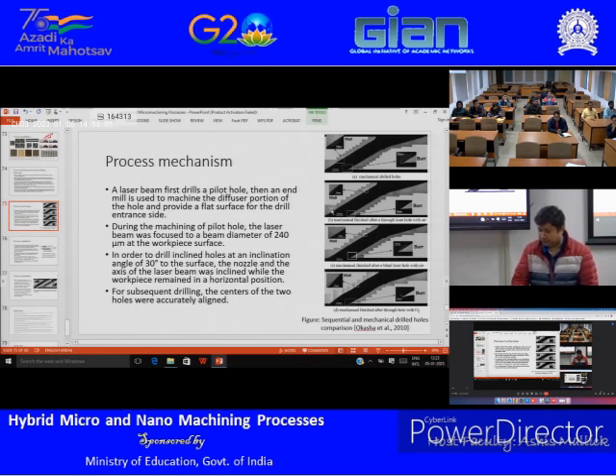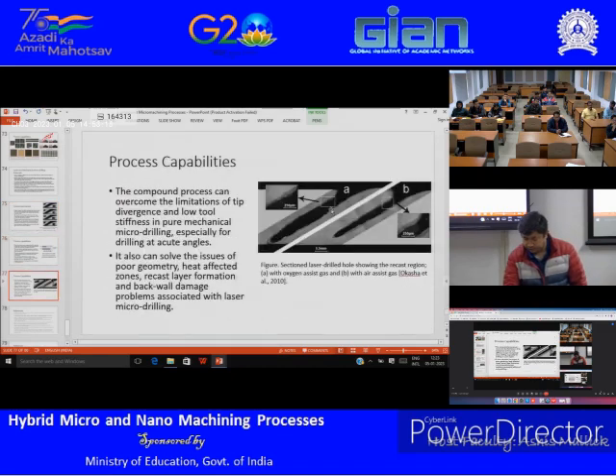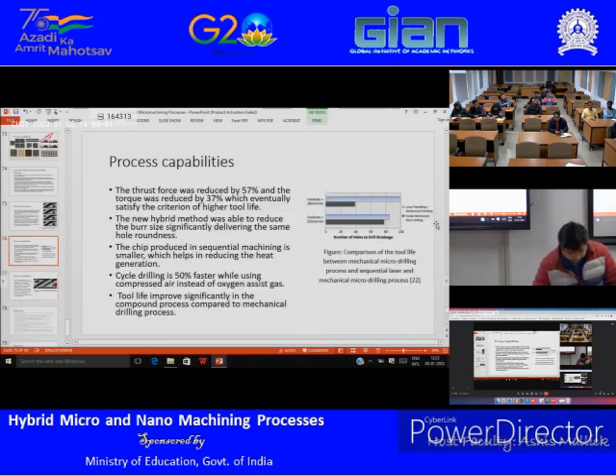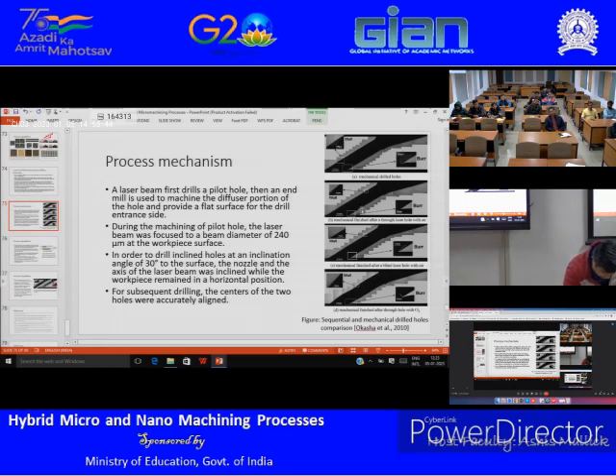All 4 cases are sequential processes with different conditions, but those others are not sequential, just the laser process only, and you see that it has some heat affected zone here, right? If you look at the inside, you see some heat affected zone. So this is the heat affected zone. And when you are using mechanical drilling followed after it, I really don't see any heat affected zone here. Not much heat affected zone.